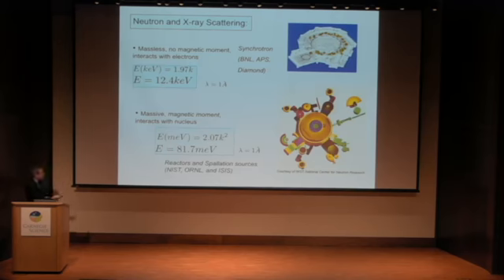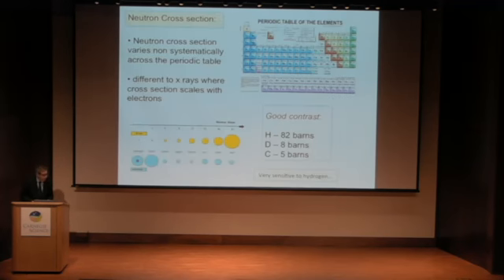So I just use this comparison here. I pick 1 angstrom just as an example of a typical length scale. If you wanted to calculate the energy of a photon with that particular wavelength, you come up with an enormous energy scale, about 12 keV. However, if you do the same thing for neutrons, because it has mass, you come up with a much lower energy scale. So neutrons are produced with the right energy scale and wavelength for the properties we want to study.